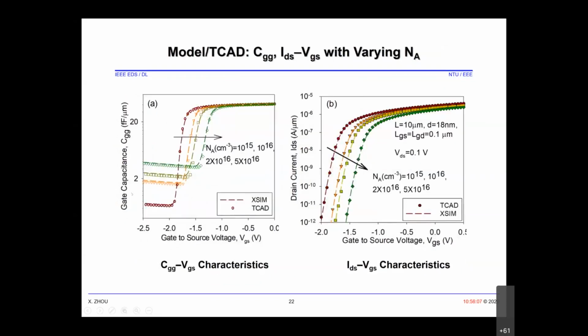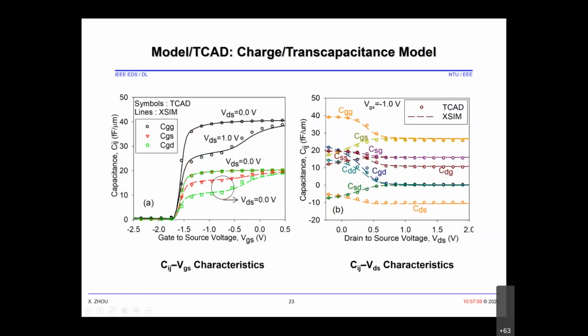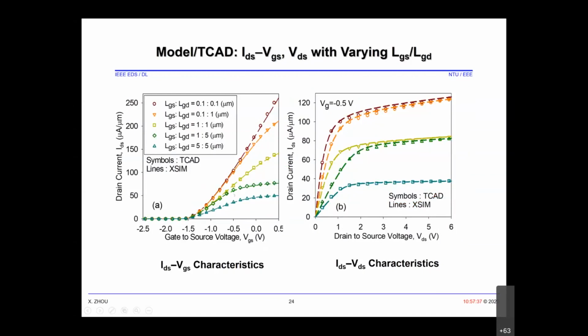Well, the corresponding CV curve, CGG versus VG, and the drain current on the left. This is showing the doping dependence, where the substrate unintentional doping changes from very low to a higher value. So we see the shift in the threshold voltage is all included in the model. Well, this one shows the geometry dependence of the access region for different ratios of gate to drain and gate to source lengths. So our model scales physically with these geometries.